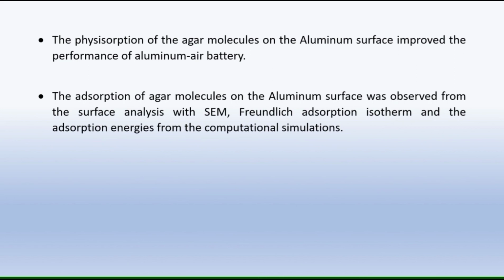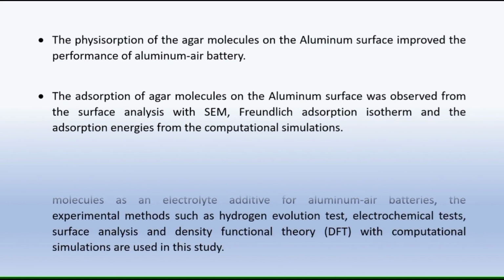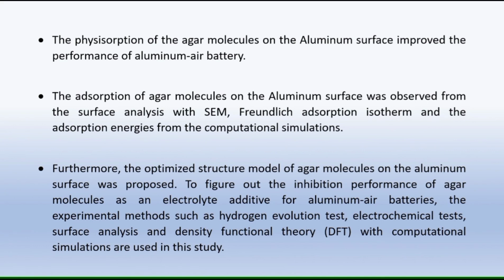The adsorption of agar molecules on the aluminum surface was observed from the surface analysis with SEM, Freundlich adsorption isotherm, and the adsorption energies from the computational simulations. Furthermore, the optimized structure model of agar molecules on the aluminum surface was proposed. To figure out the inhibition performance of agar molecules as an electrolyte additive for aluminum air batteries, experimental methods such as hydrogen evolution test, electrochemical test, surface analysis, and density functional theory with computational simulations are used in this study.